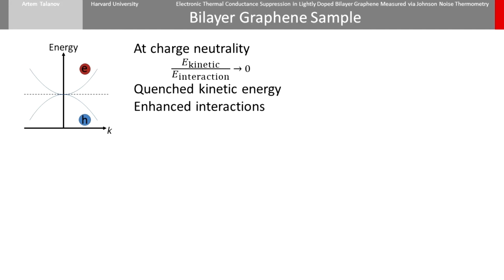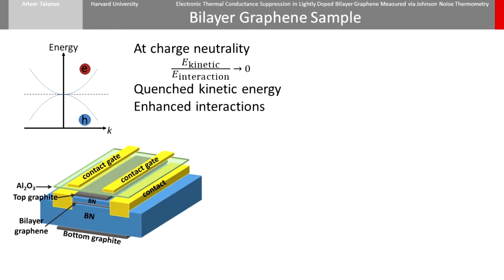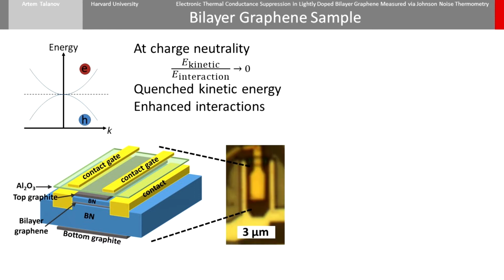What this means is that near charge neutrality, the effects of Coulomb interactions between electrons are strongly enhanced because the kinetic energy is quenched. This is the schematic of my device. The bilayer graphene is encapsulated in top and bottom hexagonal boron nitride, and that is capped on both sides with graphite gates. A contact gate near the edge strongly dopes the region not covered by the top graphite. Here is an optical image of the device.